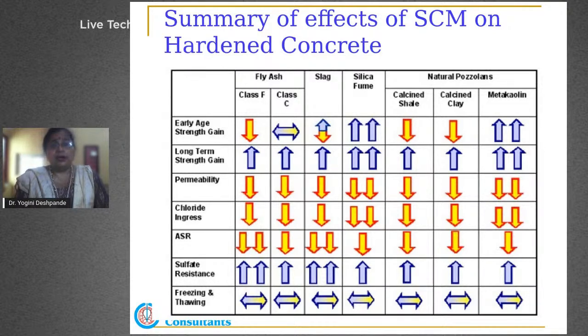Permeability - water permeability, rapid chloride permeability, all the different types of permeability issues we may have will get definitely reduced, because supplementary cementitious materials react with the calcium hydroxide generated in the cement hydration process after about 2 or 3 days. Once it starts reacting, the amount of pores developed in the concrete get reduced, helping ensure a more impermeable structure.